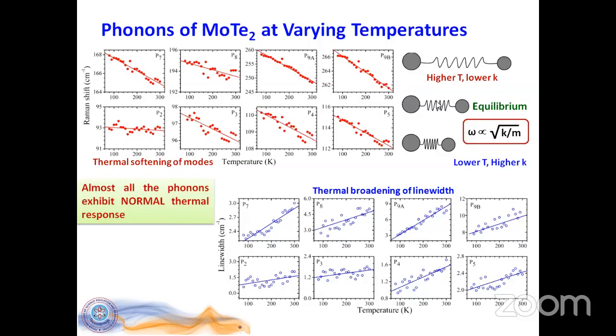One can understand that if, let's say, I assume it's a diatomic molecular system, just for understanding's sake, and this is a spring-ball model. In the equilibrium state, at higher temperature, expansion happens in the lattice. So basically the spring constant K decreases, and at lower temperature it becomes stiffer, so the spring constant becomes higher. And we know the frequency is proportional to the square root of K by M. So K is basically the key player here at high and low temperature, right? As it softens or hardens, the frequency shows the same behavior. So in other modes, there is no surprise.